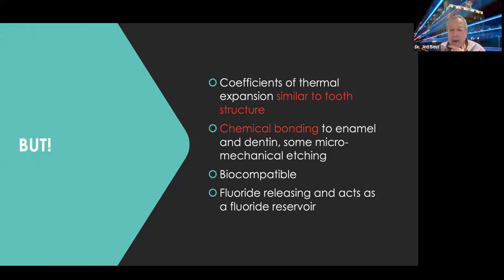So key also is that there's fluoride release. Now, it's somewhat questionable how much fluoride is released, but there is a steady state of fluoride releasing. In fact, if you look at a glass ionomer restoration that's failed, part of it's popped out of the box, and you take an X-ray, you'll notice that the DEJ line has become far denser white than the other area.